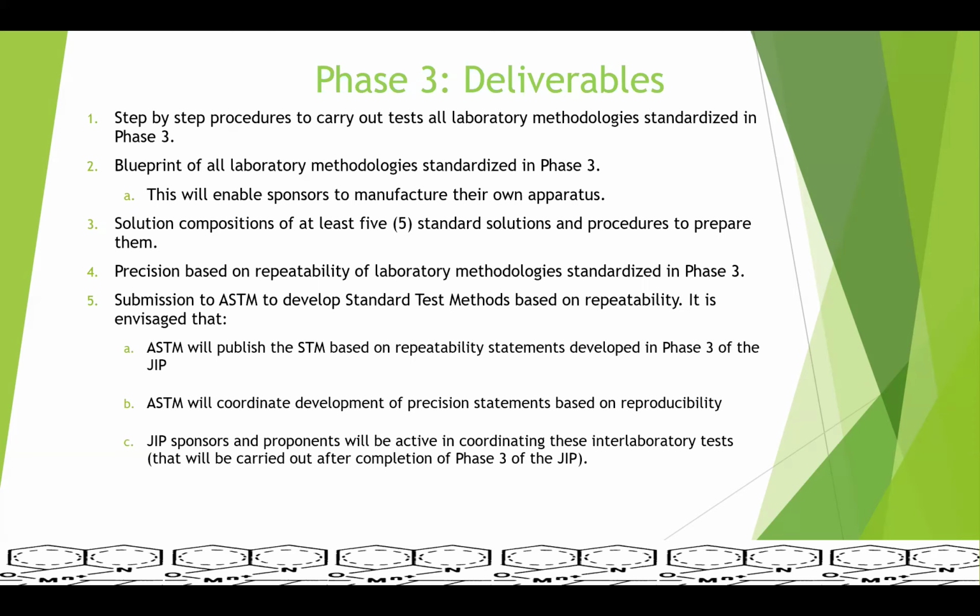One thing we found for the last 30 years is that unless you standardize the solution and the gas composition as well as procedures, you cannot develop a precision statement. So for which we identified, at least we need to standardize 5 solutions and procedures to prepare them so that the repeatability and reproducibility or the precision will be good.